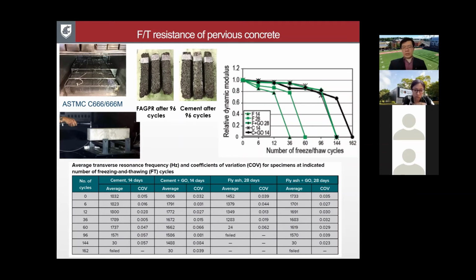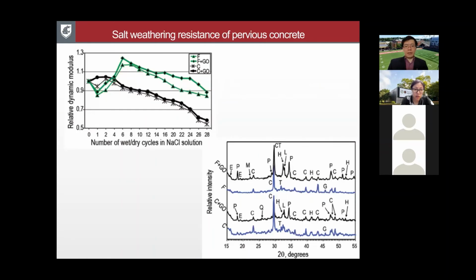And we use a non-destructive testing ultrasonic tool to capture the loss of relative dynamic modulus. Now, like I said, we separate this physical one, then we look at the chemistry, the chemical attack. So we soaked the pervious concrete in the salt solution, only going through wet-dry cycles, not freeze-thaw. So in this case, very interestingly, the resistance to salt weathering, this is a different mechanism, right? Mostly a physical attack coupled with some chemical attack.